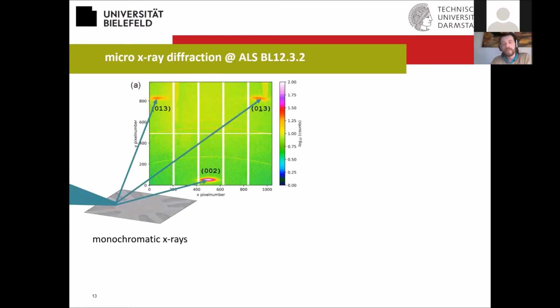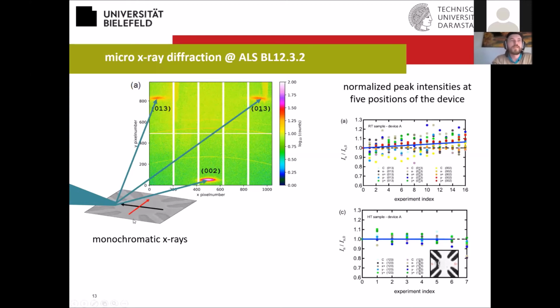Okay, so we dug deeper. Our first idea, among many that we tested, was that in these hotspots where the current flows through these narrow parts of the structure, the temperature should be pretty high during the pulsing, so that there might happen some recrystallization. Basically, it's a kind of annealing that's happening there. To investigate this, we went to the Advanced Light Source, beamline 12.3.2, where you can do microdiffraction with a spot size of about 4 micron. And we did 2D diffraction experiments looking at these spots while doing a pulsing experiment, very much the same as I've shown you before.